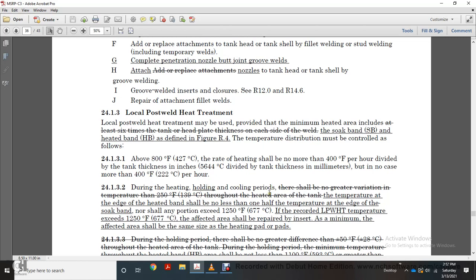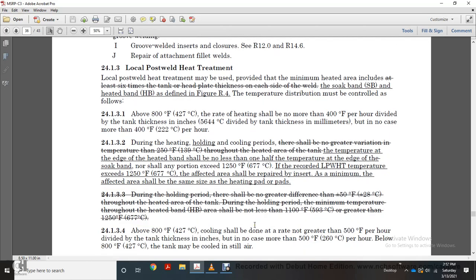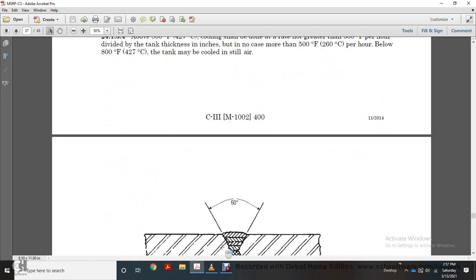During heating and holding cooling periods, the temperature at the edge of the heated band shall not be less than 1/2 of the temperature at the edge of the soak band, nor shall any portion exceed 1250 degrees. If the recorded local post-weld heat treatment temperature exceeds 1250 degrees, the affected area shall be repaired by insert. The minimum size of the affected area shall be the same size as the heating pad or pads. 24.1.3.4, above 800 degrees Fahrenheit, cooling should be done at a rate no greater than 500 degrees Fahrenheit per hour, divided by the tank thickness in inches, but in no case more than 500 degrees Fahrenheit per hour. Below 800 degrees Fahrenheit, the tank may be cooled in still air.